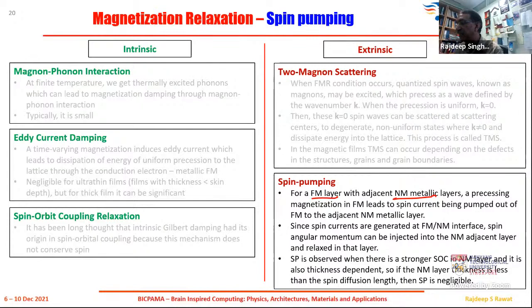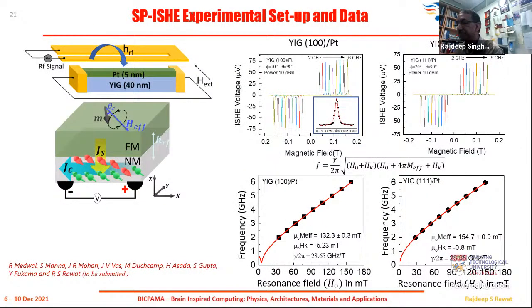Of course, there are several factors which affect this spin pumping. This is the arrangement of our experiment, where you see there is a YIG thin film, the same 40 nanometer thin film, coated with a 5 nanometer thick platinum layer. Then you have this signal line in which you have an oscillating current, which produces this time varying HRF, which in this case is perpendicular to the system. So this is along the Z axis.